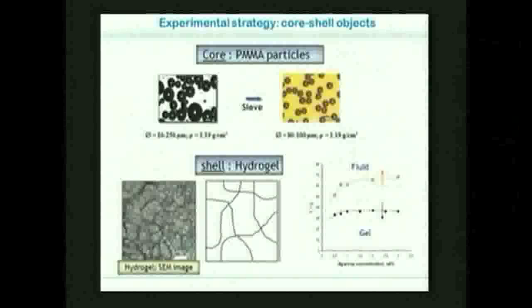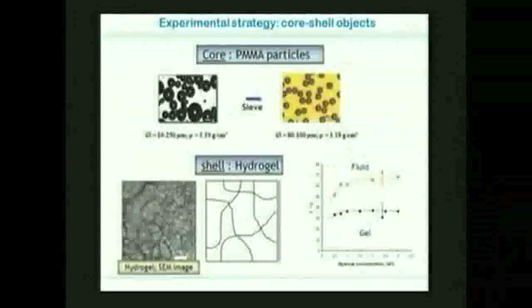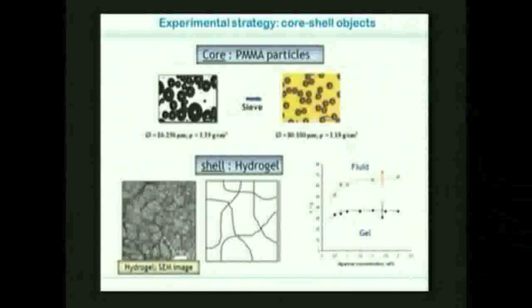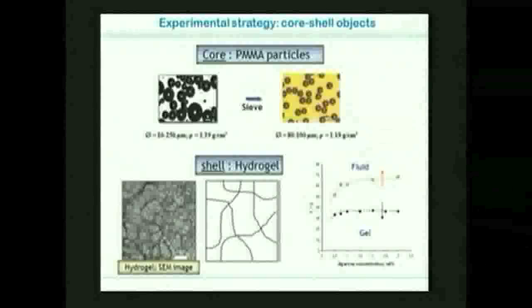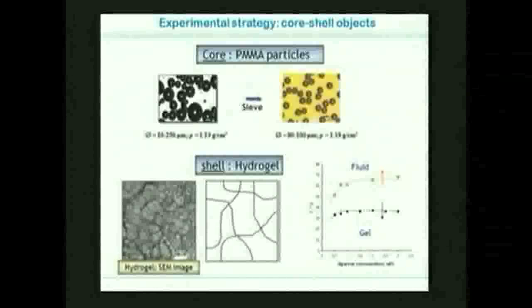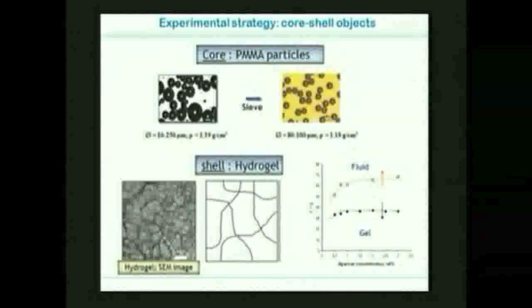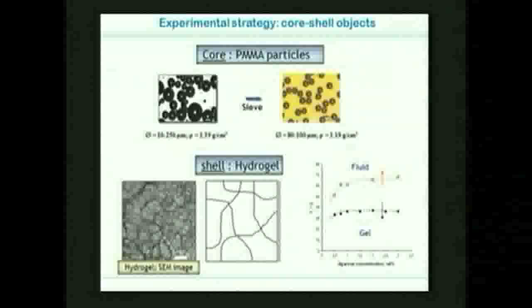These are polymer particles, which will be in the range of 80 to 100 micrometers. And for the gel, we're going to use hydrogel, which is agarose hydrogel, a gel that is very used by people who work with biology, because it is very simple to prepare. You just mix this powder with water, and you have a system which presents a fluid phase at high temperature and a gel phase at low temperature. So by playing with the temperature, you are able to tune the system.